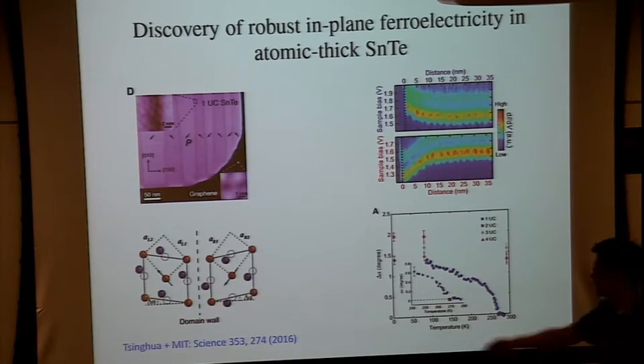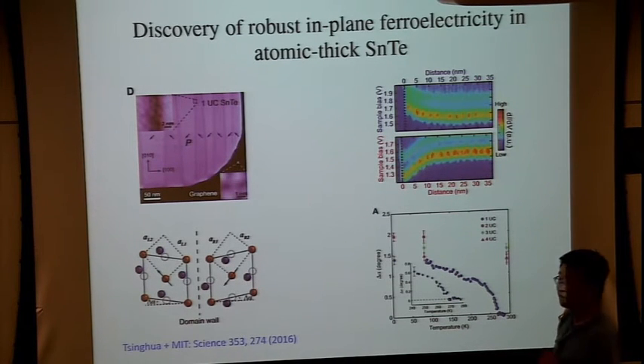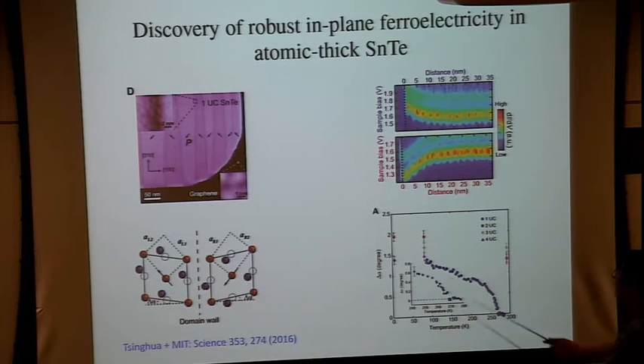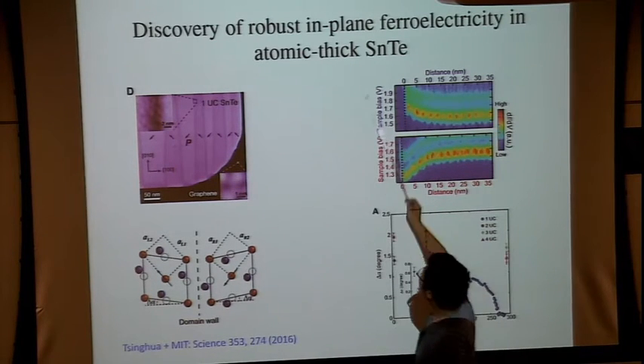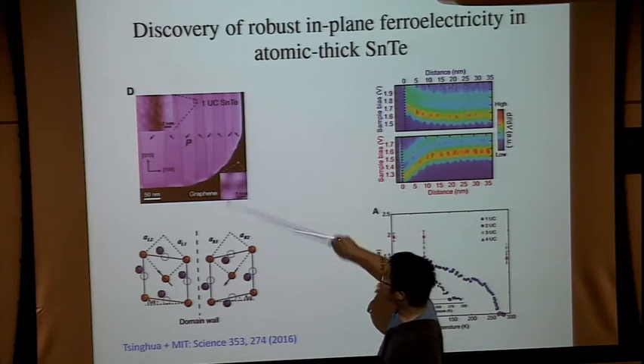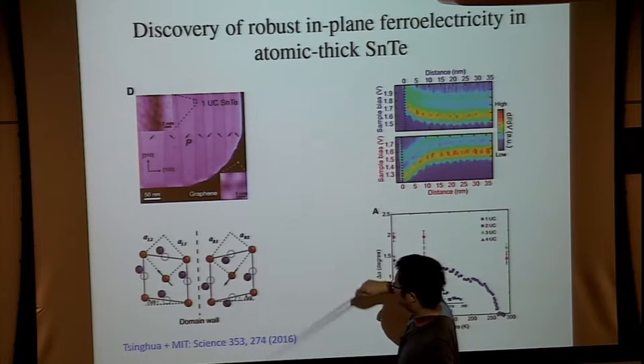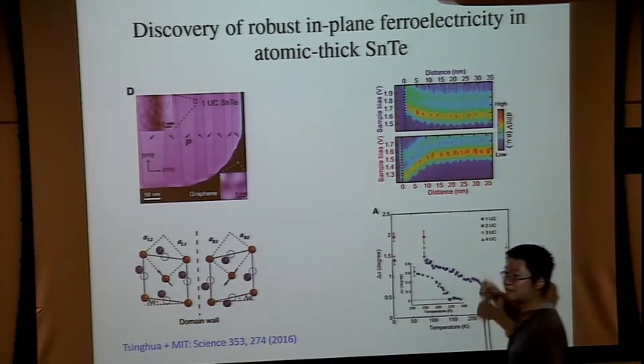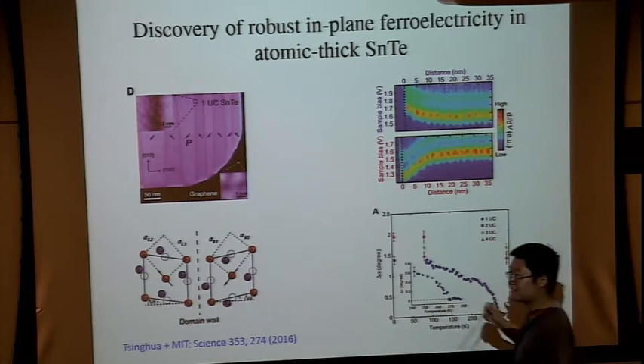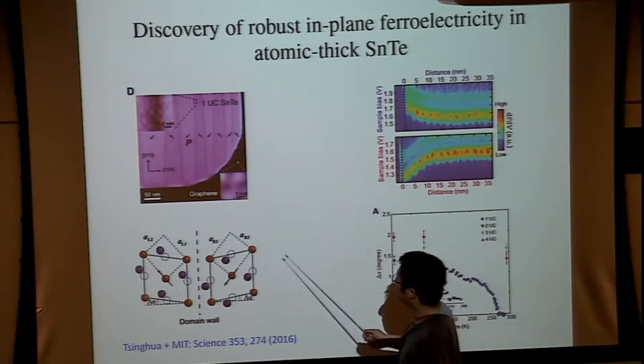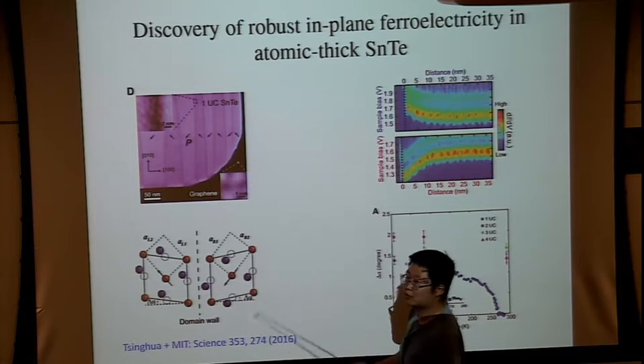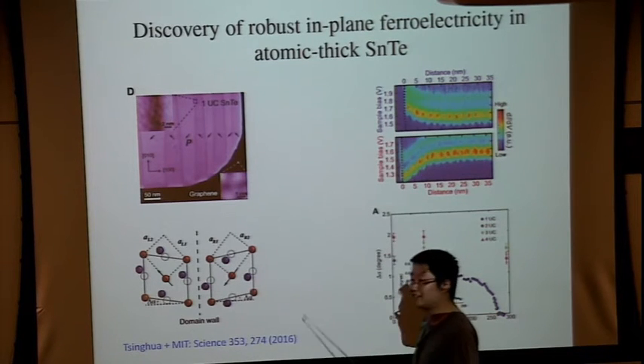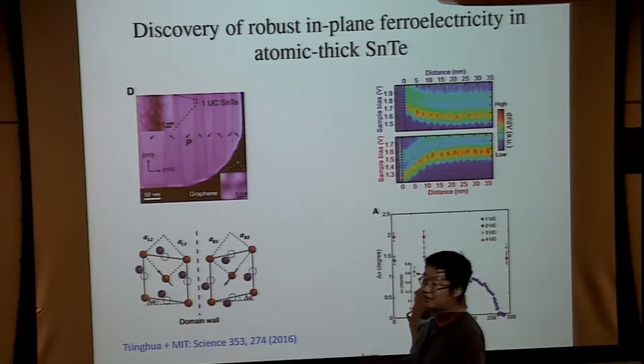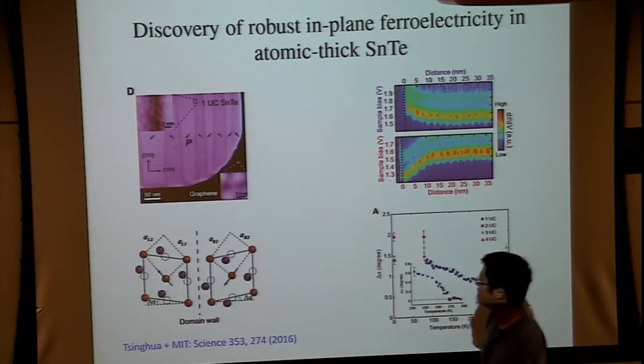So recently, together with the Tsinghua group, we studied these thin films. These are atomically thin tin telluride grown on graphene, and here's what experimenters found, an interesting surprise. That's not what we theoretically expected. As I said, tin telluride has structural distortion in the bulk. Unlike lead tin selenide, the distortion occurs at around 90 Kelvin. It's a fairly low temperature phenomenon.